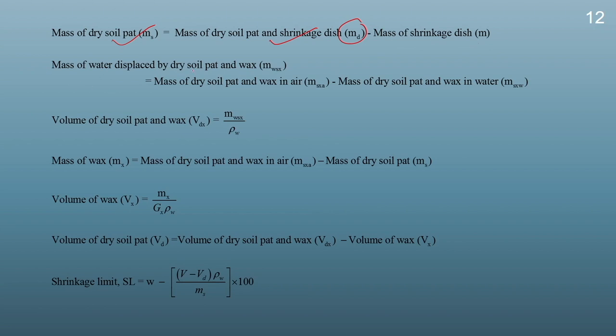Then the mass of the water displaced by the dry soil pad and wax, MWSX, will be equal to the mass of the dry soil pad and wax in air minus the mass of the dry soil pad and wax in water. Then the volume of the dry soil pad and the wax, VDX, will be equal to MWSX divided by rho W, where rho W is the unit weight of water. Then the mass of the wax, MX, will be equal to the mass of the dry soil pad and wax in air, MSXA, minus the mass of the dry soil pad, MS. Then the volume of the wax, VX, will be equal to MX divided by GX into rho W, where GX is the specific gravity of the wax.